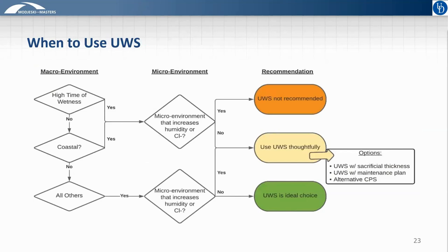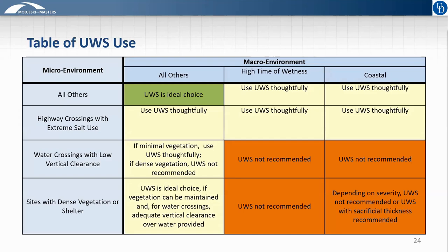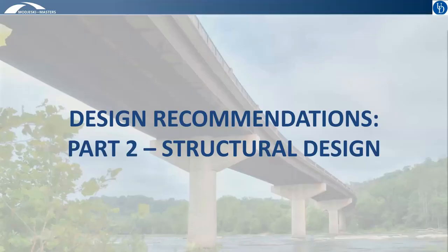So tying all those details together, we return to the flowchart that I showed at the beginning, where the micro environment and macro environments are quantitatively considered to result in a recommendation on the use of uncoated weathering steel. We can also illustrate that same concept in table form, where the combinations of environments where uncoated weathering steel is not recommended or where the thoughtful use of uncoated weathering steel is recommended are clearly identified. And here I'll note that while those categories occupy most of the space on this table, the vast majority of cases will fall into the all other category for microenvironment and the all other category for macroenvironment. So we'll end up in the green square here, resulting in the recommendation to use uncoated weathering steel in most cases.